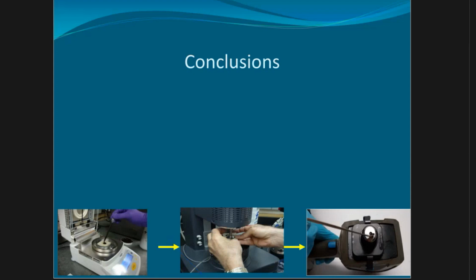I think the second step he's done is recovering RAP in the field, but he's doing destructive testing. What he's done is very good, because he's able to go in the field and in 8 minutes, I've seen this, extract the binder. It's a micro extraction in the field. He injects it, and he has the infrared right there. He sticks it on the ATR, attenuated total reflectance, and measures it. We have some papers on this.